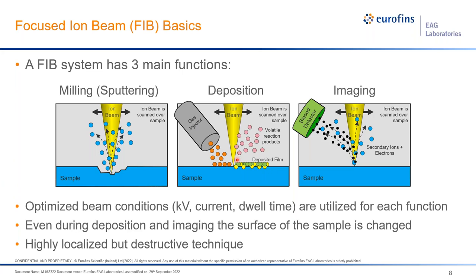It's also important to note that all FIB deposited material incorporates impurities from the incompletely decomposed precursor gas, as well as the incident ions from the FIB. So if we're depositing a platinum film here, it's going to be a film composed of platinum plus carbon and some gallium from the FIB as well. And then lastly, we can utilize the ion beam for imaging, where we collect either secondary ions or more typically secondary electron images of our samples.